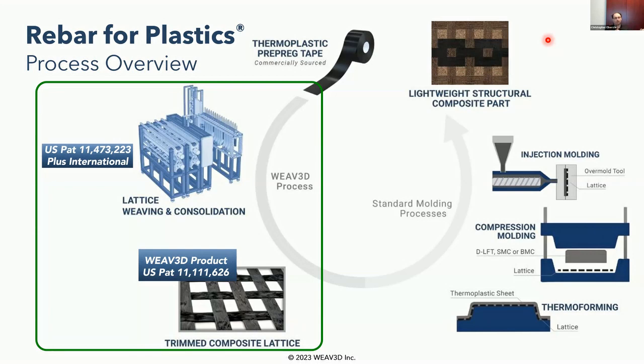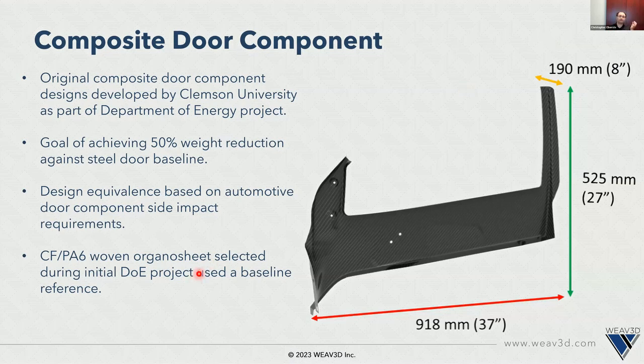In this case, it's a natural fiber polypropylene and a carbon fiber polypropylene. The carbon fiber polypropylene actually has variable spacing, so it's denser in the middle, then the spacing goes a little bit more sparse as you go to the edges. This kind of localized tunability gives you a lot of control over where you put the material and how much material you use. To give you a practical example, this is the automotive beltline stiffener part